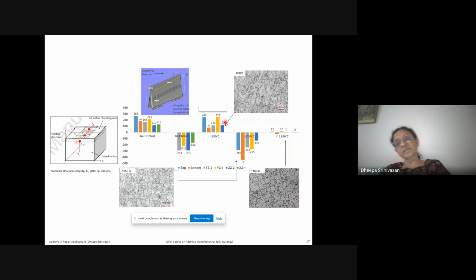Then when you heat treat it to 950 degrees, this is the microstructure of this, which is again a little bit of tensile. And when I heat treat it to 1150 degrees and cool it, for this equiaxed structure, it has a maximum compressive residual stress. So this is all through thickness measurement.